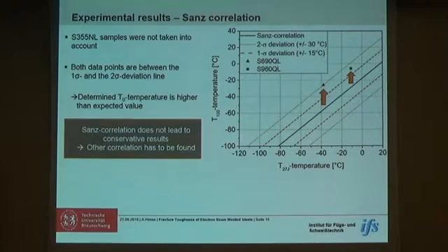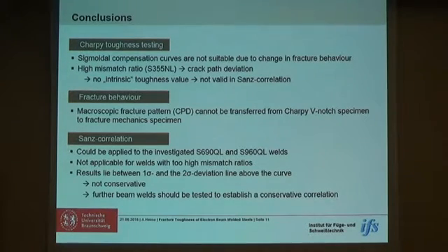We could use the data points for the S690 and S960 in this kind of correlation, and we can see that the determined T0 temperature is much higher than the expected value. We have values between the 1 sigma and 2 sigma deviation line. That shows that the Sanz correlation does not lead to conservative results in our case, and another correlation has to be found. As we don't have that many points, we weren't able to find a correlation yet, but that is part of the research that is going on right now.